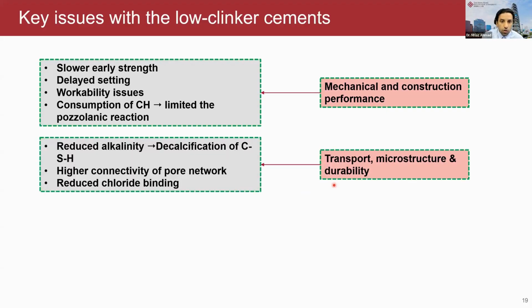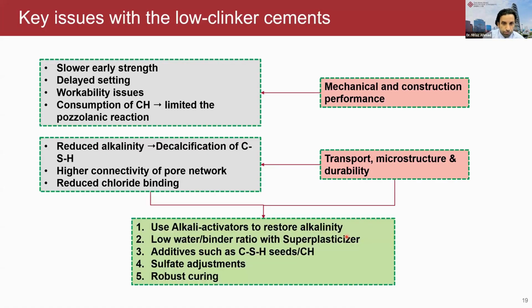This is partly because there is less cement, which generates Portlandite, and this is responsible for the pozzolanic reaction. On the durability side, we also face some issues. When we replace a higher volume of the cement with supplementary material, the cement has a very low pH. This reduced alkalinity can lead to problems such as the decalcification of CSH because of natural carbonation, or it can lead to more porous structures, which can degrade the long-term durability, which is very important for concrete.